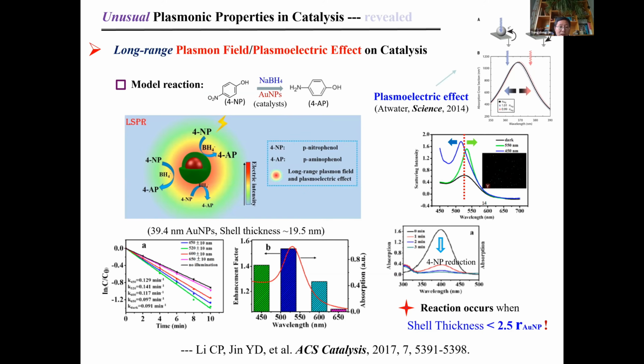We found that also in our system, where the gold nanoparticle has been encapsulated by a compact, pinhole-free silica shell. The reaction occurs when the shell thickness is smaller than 2.5 times the radius of the gold nanoparticle.